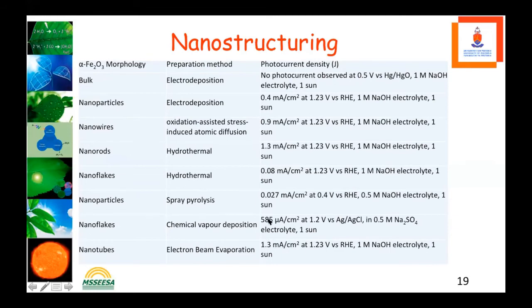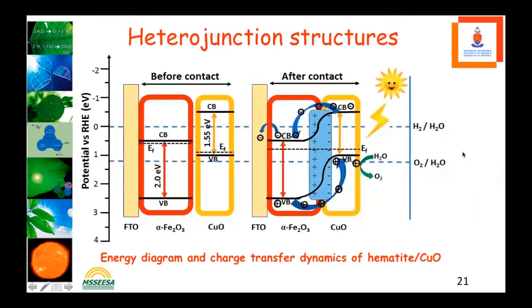You can see that the photocurrent can increase. Look at the nanorods, 1.3 milliamps, and also nanotubes, 1.3 milliamps. So we can use the nanowires and nanotubes to make our hematite. So these are heterostructures where in our lab we have used copper oxide and iron oxide onto fluorine-doped substrate, and we have found that the energy transfer has been very good using the solar energy.